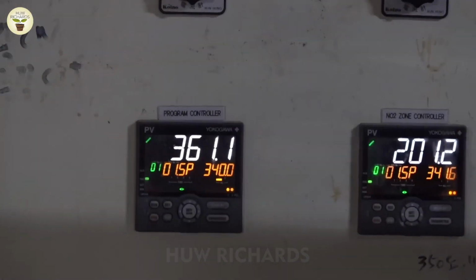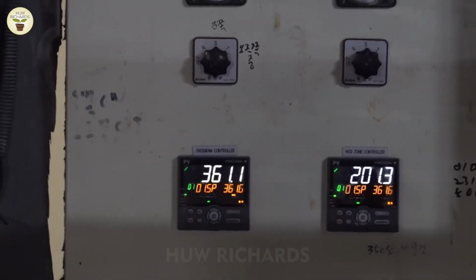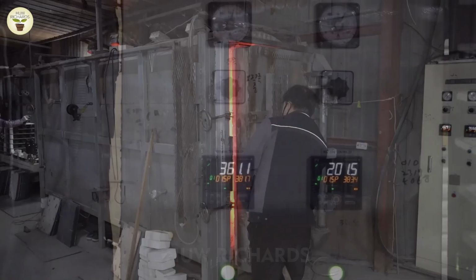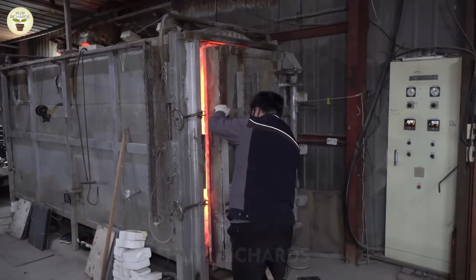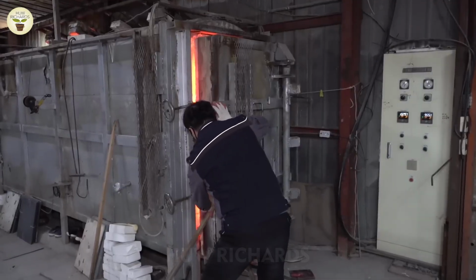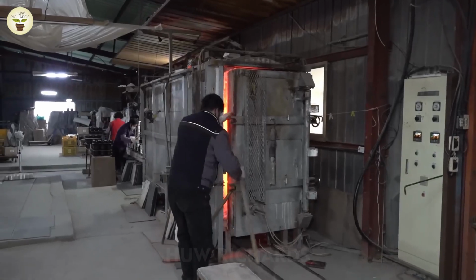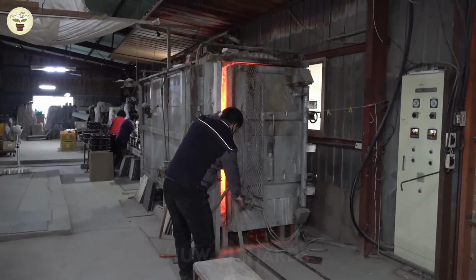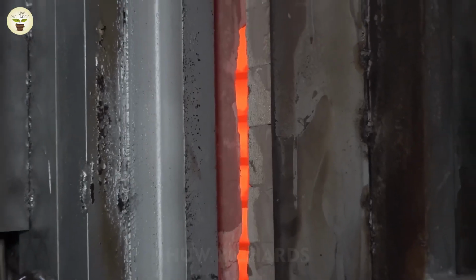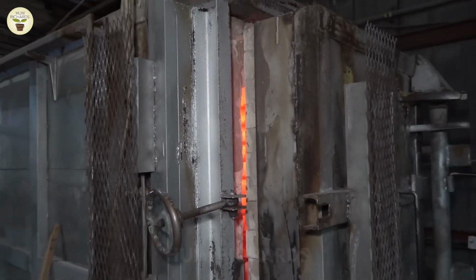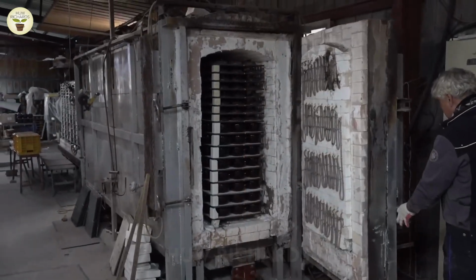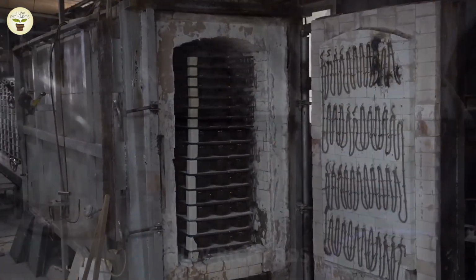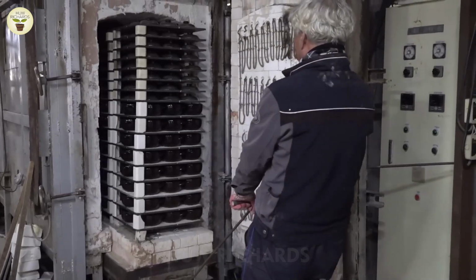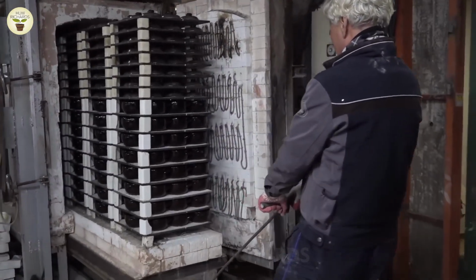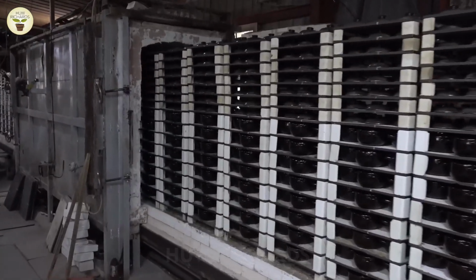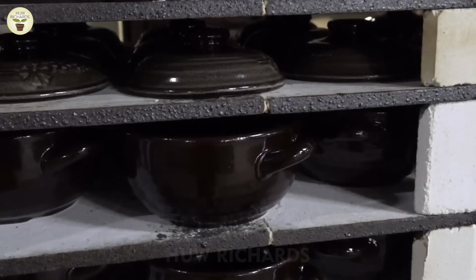They will stay in the kiln for several hours at temperatures ranging from 1000 to 1200 degrees Celsius. At this high heat, the clay undergoes a structural transformation, becoming harder and more durable. The glaze on the outside will also melt and fuse perfectly with the pot surface, creating a smooth and resilient coating. The combination of high temperature and extended firing time ensures the product reaches its highest quality, ready for long-term use.